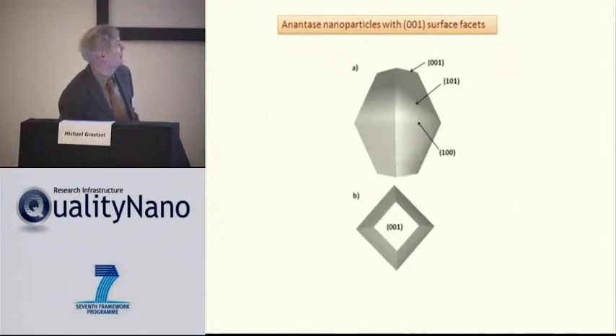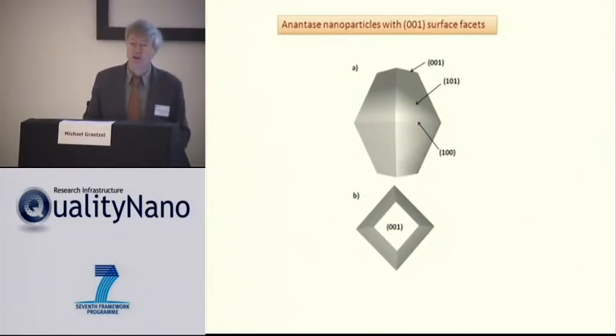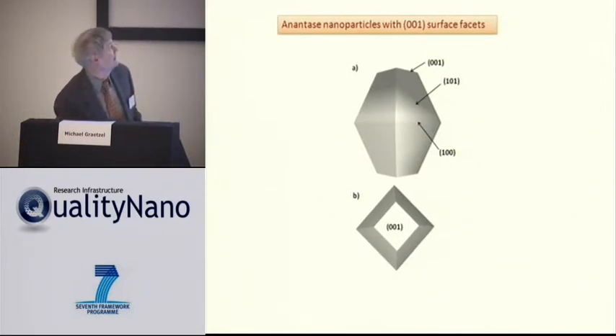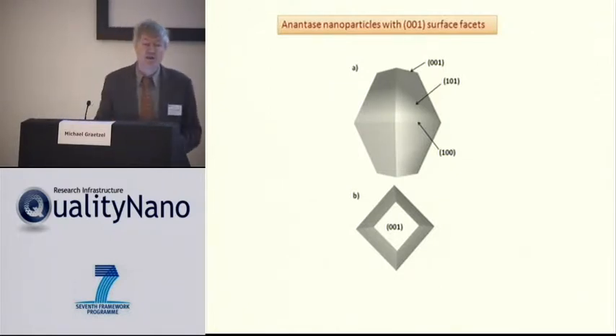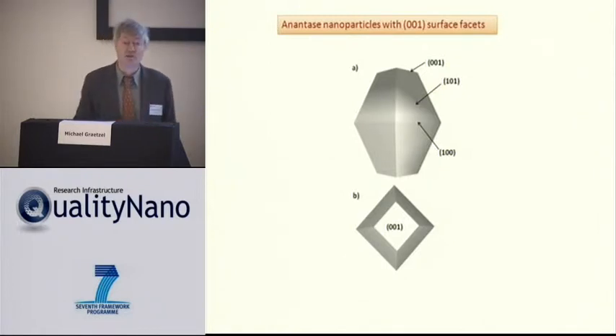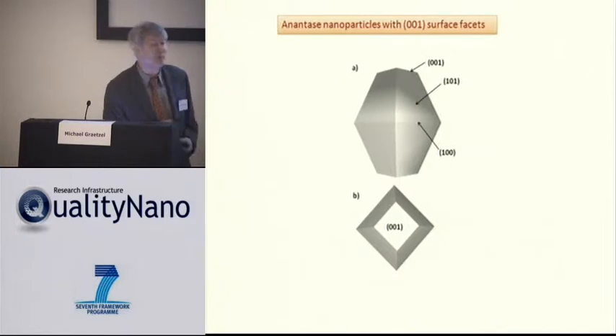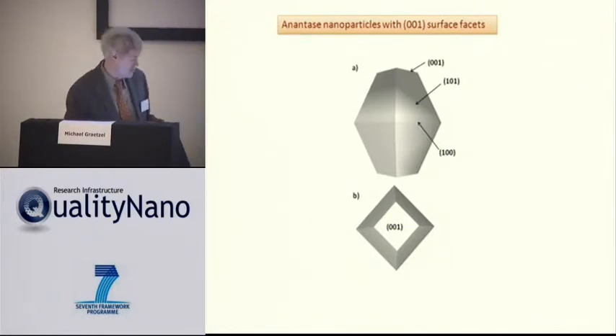I skip over this. Some other, these are new nanostructures where I think that's something this audience would be interested in. In the future, we will synthesize high quality nanoparticles. High quality is very important. What does that mean? Well, the faceting of the nanoparticles. TiO2 anatase has a prevalence of 101 facets. That's the lowest energy facet, but the surface plane 001 has actually an advantage in photovoltaic conversion. So you would rather like to use the 001 platelets and not those particles with the 101. So these are questions that are already being worked on, and synthesis methods are developed to get the highest quality nanoparticles.